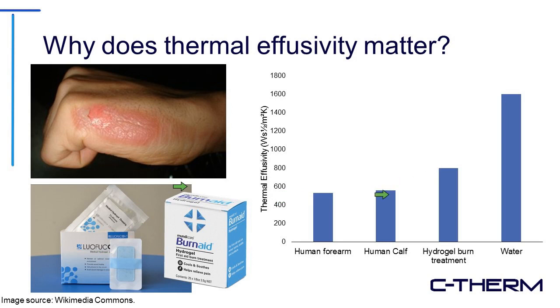So effectively what you're doing in these hydrogel materials is cooling the burn. But we don't want to cool it too much. So we have water here around 1600. We want to tune the effusivity so that we're not discomforting the person that's being treated, but we're also effectively cooling their burn itself.